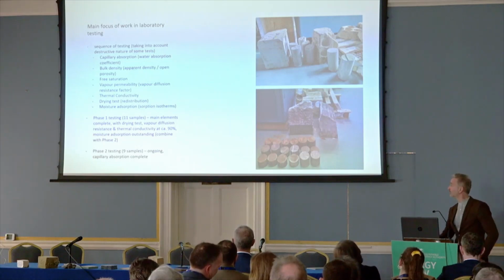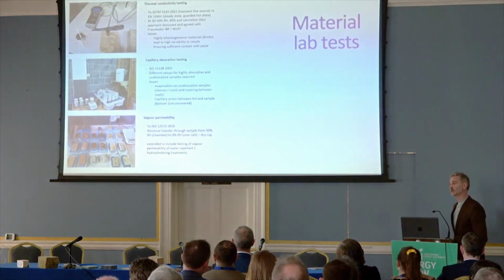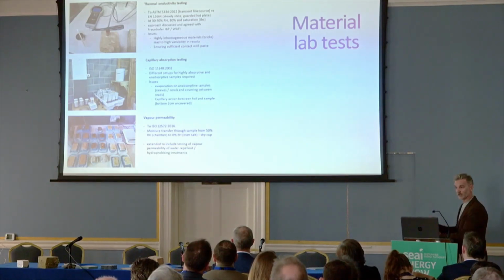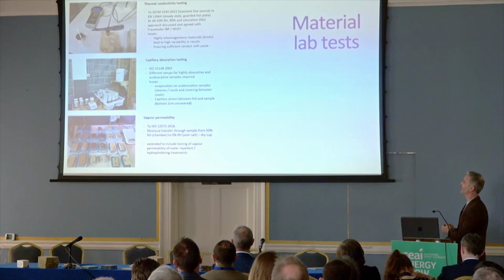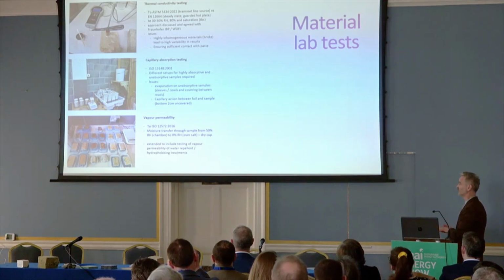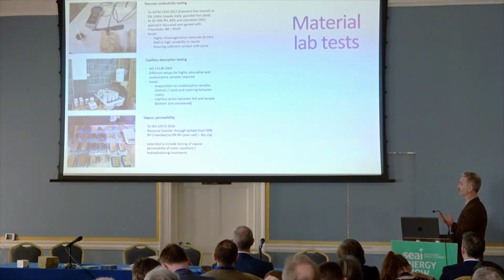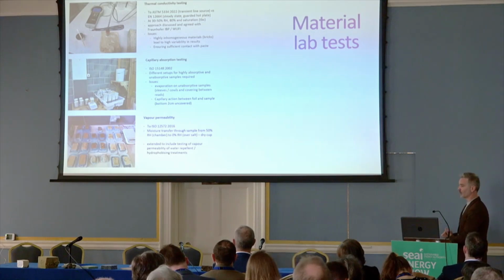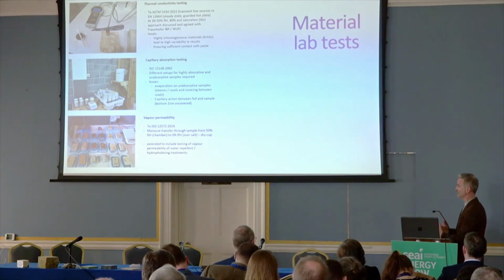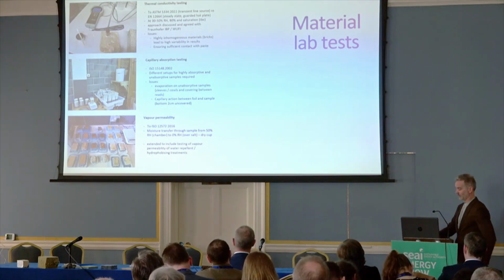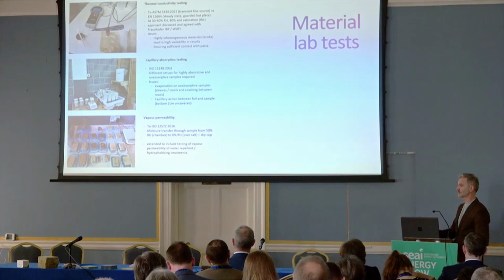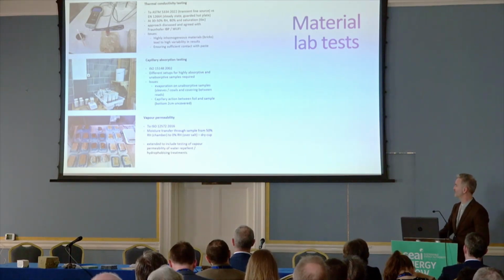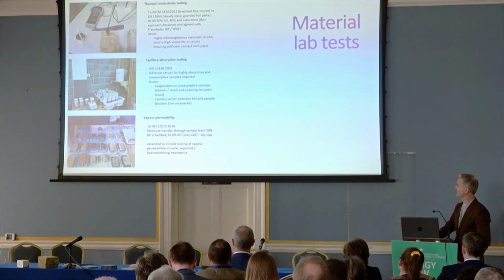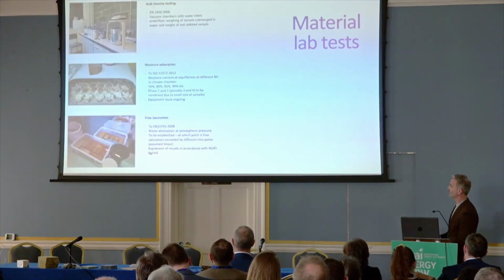The tests that we're doing include thermal conductivity testing, which is a key test to understand heat transfer through the materials. The capillary absorption test, where we're monitoring the uptake of water through the fabric, is a property relevant for driving rain or heavy surface moisture buildup. Vapor permeability, in contrast, measures the permeability of the material to vapor movement through the sample. All of these are done to standards. In certain cases, we've had to adapt to suit the nuances of traditional materials, and we've done this in conversation with WUFI in many cases.